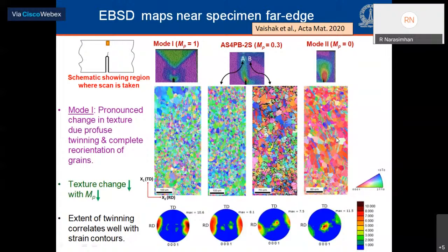In the mixed mode case, we took the scans at 2 locations. We look at the top right side, middle image in the DIC map. We have marked location A, which is inside the strain band, and B, which is just outside the strain band. So if you look at location A, the EBSD map is very similar to the mode 1 case. Lots of grains completely reoriented, massive texture change. On the other hand, if you just step a little bit out of that strain contour band and take an EBSD scan, what you see on the right side, middle, you see much less twinning and much less texture change.